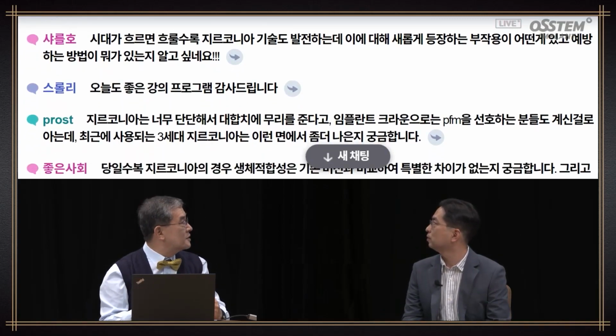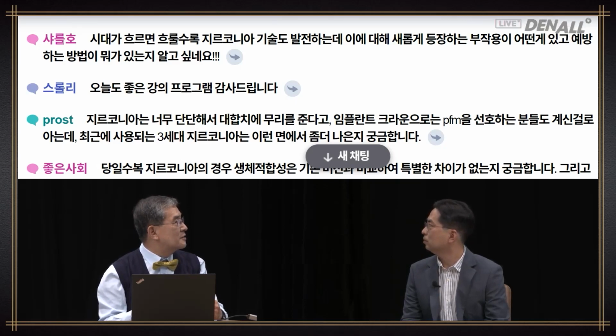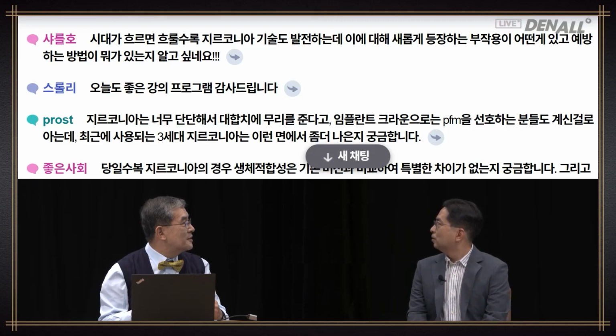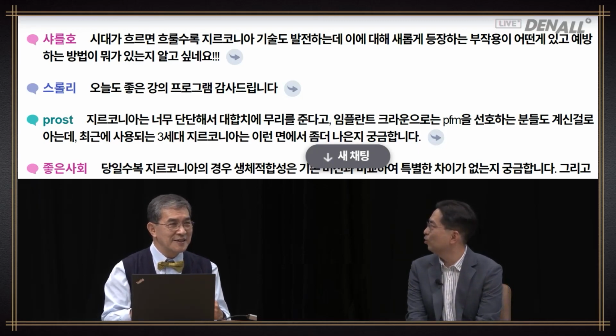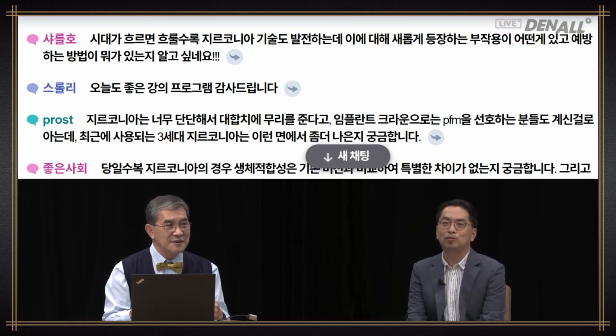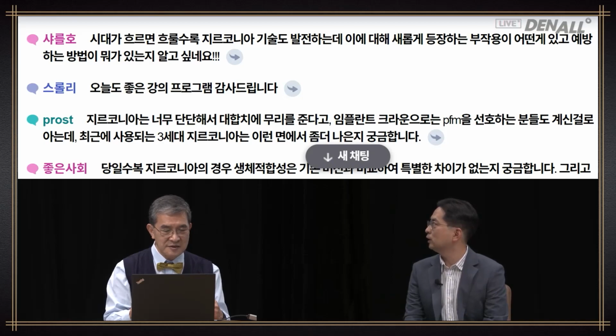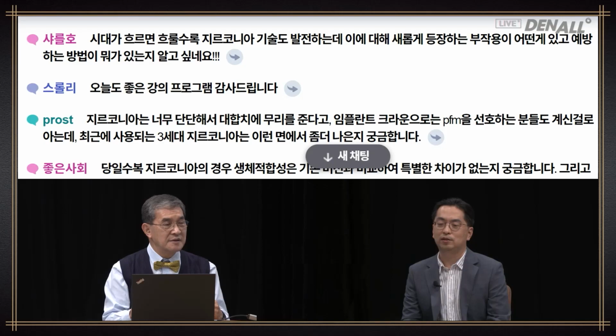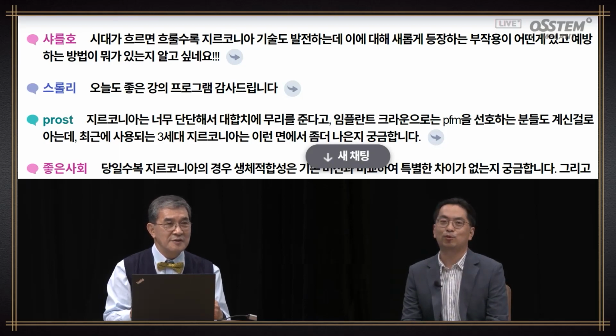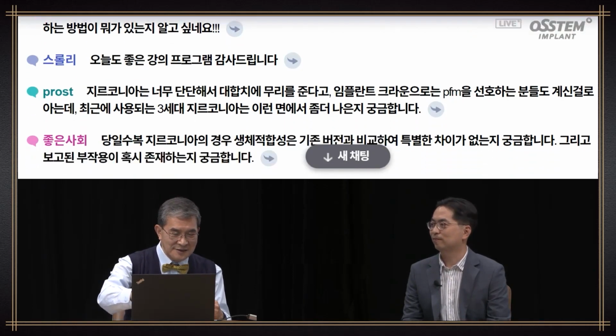Shuttle hole: with time, zirconia technology is advancing. What is the newly emerged side effect, and how can I prevent it? With the advances in technologies, I think the side effects will be reduced. As more clinicians have more experience, information is shared as to how side effects can be resolved, and because of such accomplishment, no major side effects have surfaced. In the past, we used a 3-mole yttria zirconia. It was quite hard and there was much less fracture, but when there was an issue, it was very difficult to remove it. In the case of 4-mole or 5-mole yttria zirconia, the frequency of fracture has increased, but you can remove it more easily. It is a double-edged sword.